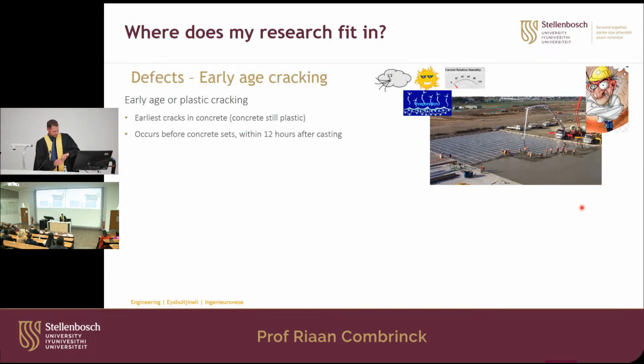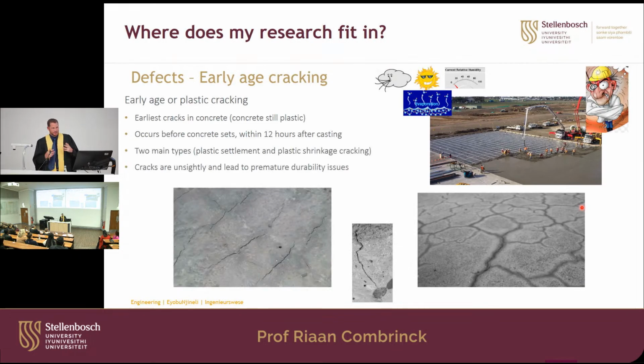Okay, so early age cracking was where I did my PhD, so I did a lot of work on that. This is the cracking in concrete in the earliest stage, while the concrete is still plastic, before the concrete sets, normally 12 hours after casting, so it's really fresh concrete. It's normally in concrete slabs like this, where you have a high evaporation rate and some reinforcing steel, which is your restraint, and that makes the concrete crack. And this happens very, very early, once you've cast the concrete.